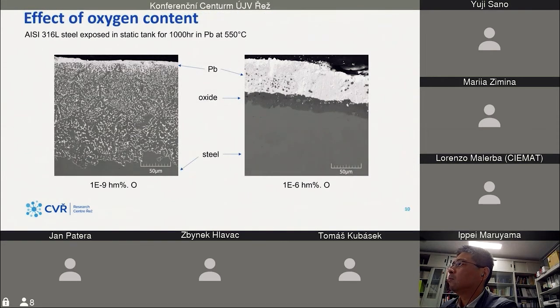The effect of oxygen can be demonstrated on these pictures. On the left, there is virtually no oxygen, so there is no stable oxide forming in these conditions. And you can see that after 1000 hours, nickel is leached out in an unacceptable manner. Even though this is very high temperature for stainless steel, with some oxygen you can develop some oxide barrier that prevents this from happening.